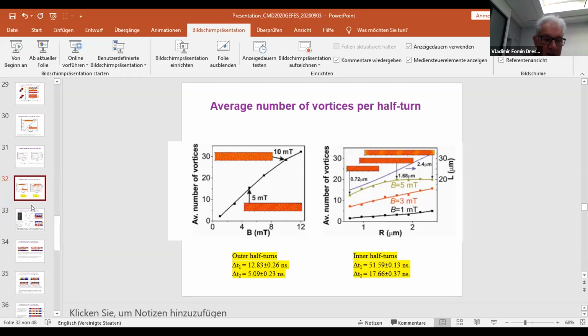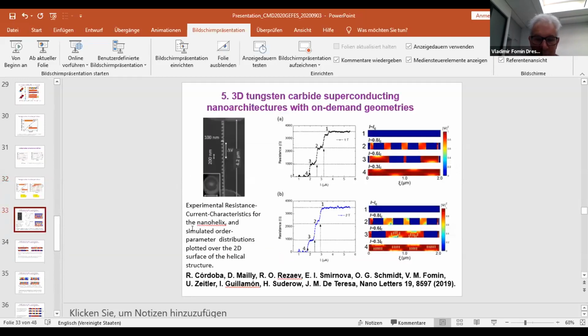And this brings us already to the last point of my presentation. It's experimental detection of shelves in the resistance versus current characteristics in such tungsten carbide superconducting nanoarchitectures which were produced by focused ion beam deposition. There are a few steps if the measurement is just on 2 windings. And our calculations here, which provided some interpretation to this experimental observation in some nanohelices. Here it's 1 Tesla, here is 2 Tesla.